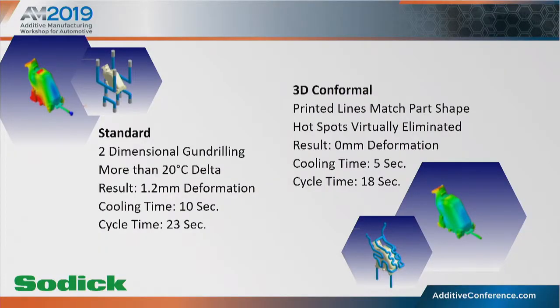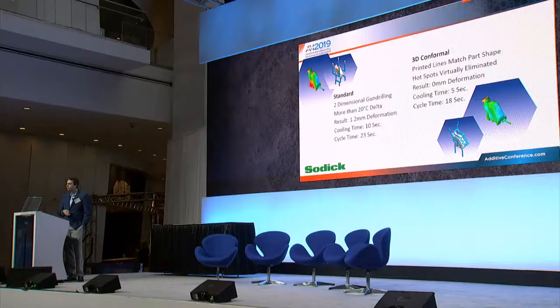So looking at one example, this is a seatbelt clip that we've actually been producing as Sodick for one of the large automotive manufacturers. In our original design, we used standard two-dimensional gun-drilled water lines. But that design had about a 20-degree delta from the hot spots on the surface of that mold to the coolest points on the surface of that mold. And what that ended up doing is it gave us deformation of the part that was more than a millimeter and a relatively long cycle time for what the part was.